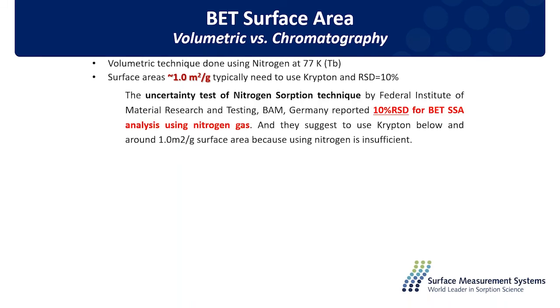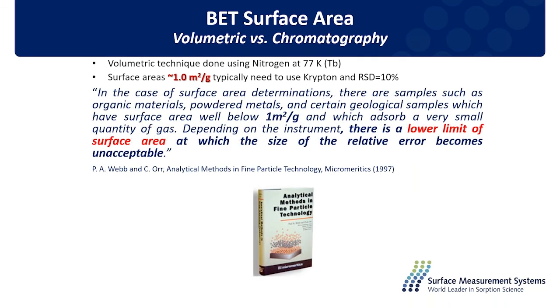It was studied by the Federal Institute for Material Research and Testing in Germany. So this is what they reported: nitrogen sorption has a 10% deviation at low surface area. Also, Micromeritics is aware that there's a lower limit of surface area that they can measure. It's a technical limitation due to the nitrogen and the vapor pressure of the nitrogen.